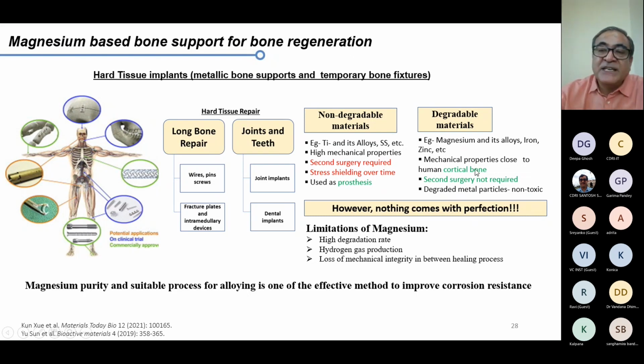One of the major limitations, and the reason why magnesium is still not in the clinics for orthopedic application, has been the high degradation rate. An orthopedic surgeon would like to have an implant inside the body for a minimum of 1 year, or even 2 years, depending upon the type of defect. So the magnesium implant which you put there should stay that long and not lose its mechanical property.